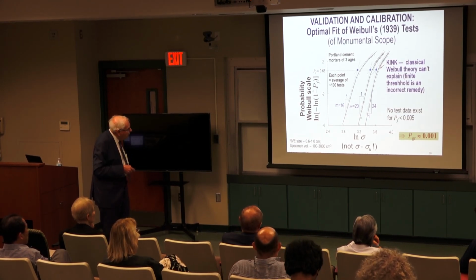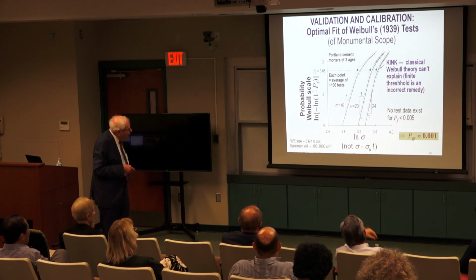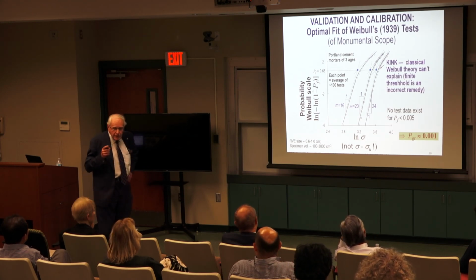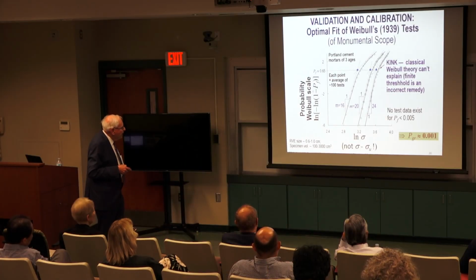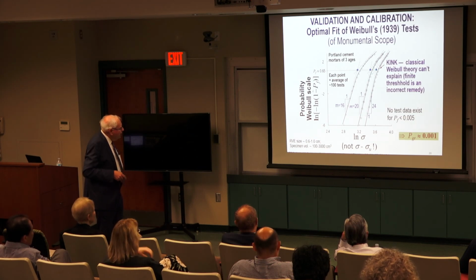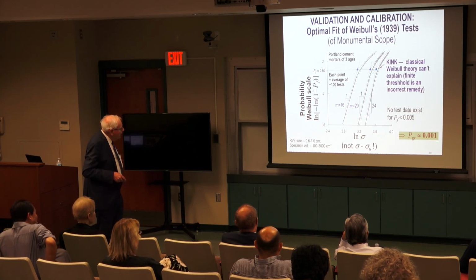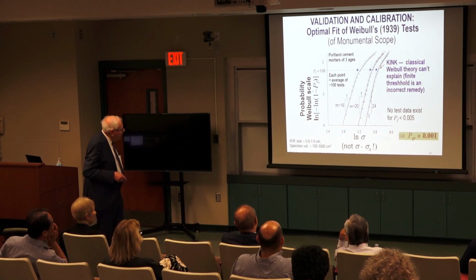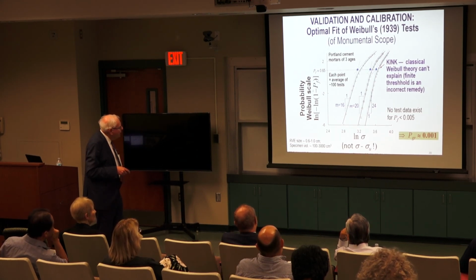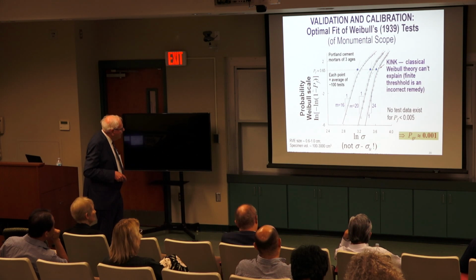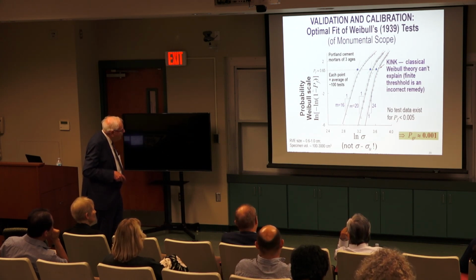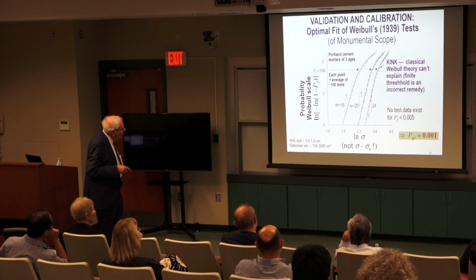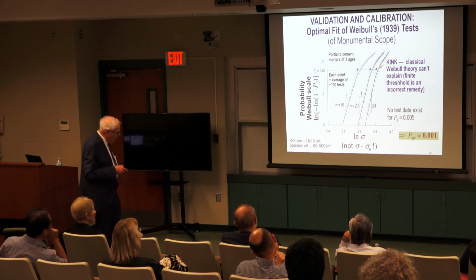Normally you don't see that. That's because each point is an aggregate of 100 tests, the average amount. If you put individual tests, it will be jumping up and down. There will be some scatter. And also here, we verify that the transition which occurs from size effect, you get at this point, and we plot it perfectly. People try to, the fit improves if you put a threshold. In fact, Weibull pointed it out himself, but you fit it a little bit and then it does not work anymore.